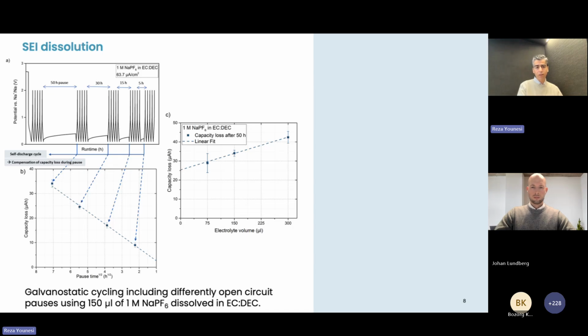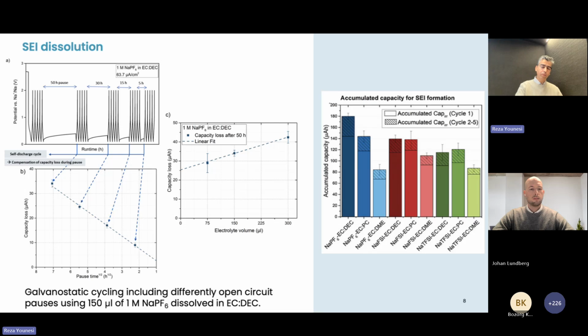If you plot the capacity loss versus the volume of the electrolyte, as you see in the figure on the right, then you can see that there is again a linear relation, which again indicates that the higher the volume of the electrolyte, the higher the capacity loss due to SEI dissolution is, which again confirms that this is a diffusion-based phenomenon.